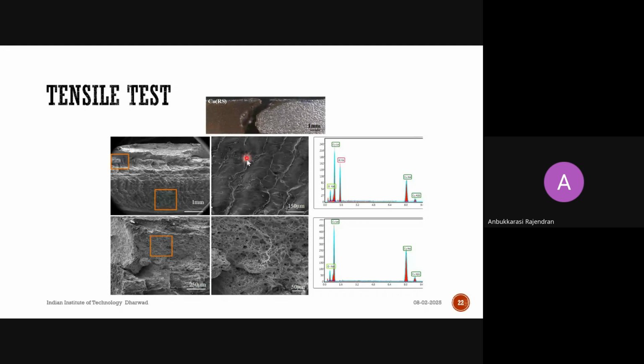Wherever it failed with brittle nature, we can see the flat mode of fracture. The ductile fracture has the dimple appearance. For the flat region, when we did the EDS analysis by selecting an area, here we didn't do a spot. We selected a big area and we could see both the copper and aluminum peaks, the spectrum of copper and aluminum, from this fractured surface. So it indicates that the failure must have been along this intermetallic layer. In the same way, when we did the area EDS analysis on the other region, the spectrum we got was only from the copper metal, meaning the region is entirely covered by copper.